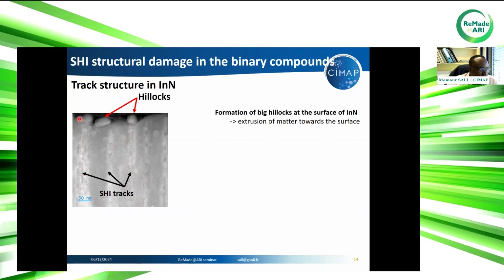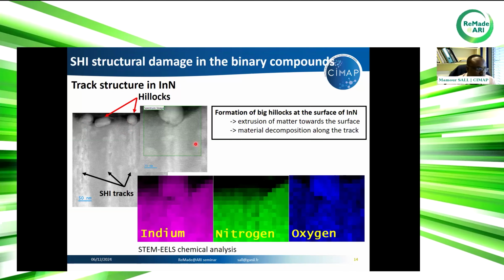And on the top of tracks, here at the surface of the material, you can see these hillocks. So these hillocks are well known in many materials. This is due to extrusion of matter towards the surface. In fact, if you remember what I showed before about track creation, inside the track, the material is hot because it's melted. It's under high pressure. And the surface here will offer a degree of freedom for releasing this pressure. That's why we have this ejection of matter towards the surface and formation of these hillocks. And in indium nitride, this is very particular because the hillock size is very big compared to other materials.